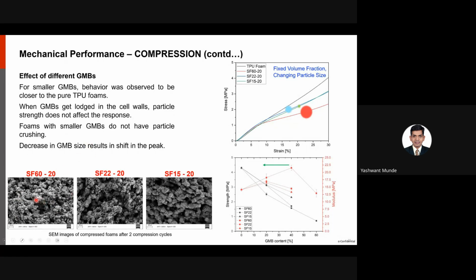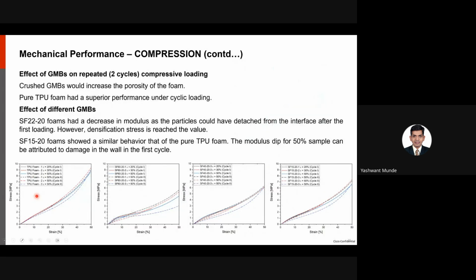I'll talk more about this next. We performed 2 cycles of compression loading to understand whether the particles have crushed or not. As we can see in this first figure, this corresponds to pure TPU. We load the structure first to 30% and then unload it. And then in the next cycle, we load it to 50% global strain. So here we see that with the larger particles,